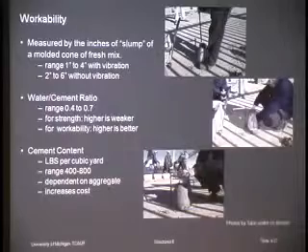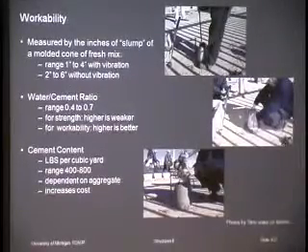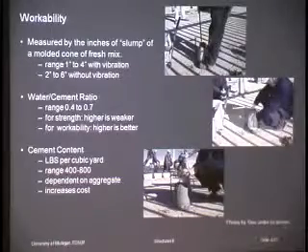You put this rod across the top of the cone, and then you measure from that rod the amount that the concrete slumps, and that is called the slump measurement. And that slump is used as a gauge of the stiffness. If you have a low slump, like a slump of 1, that would be 1 inch. That means it only dropped an inch. That's not very much. That means there's no way you're going to cast that into a slab.